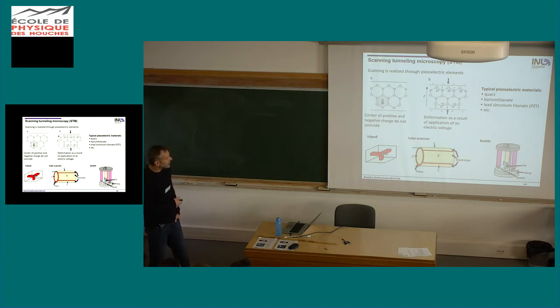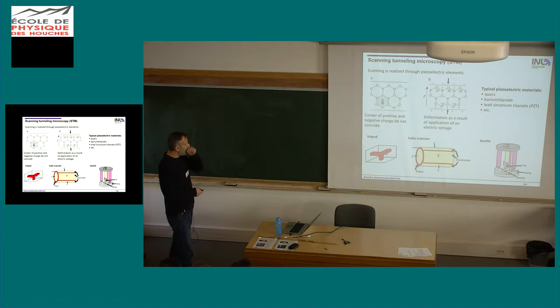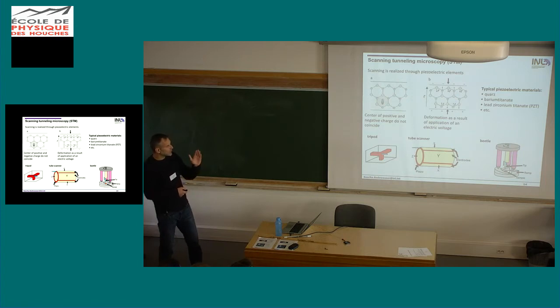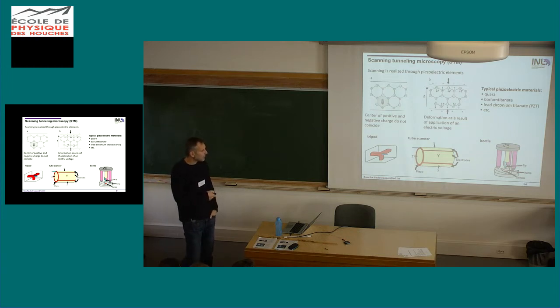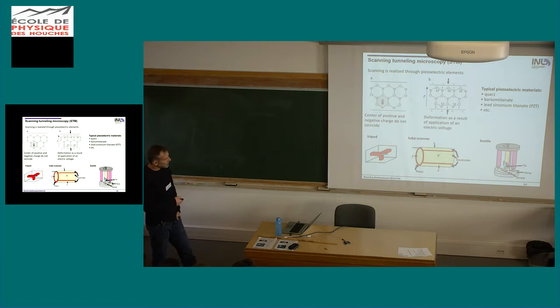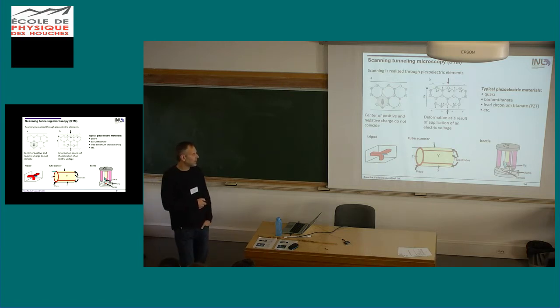And these piezoelectric elements can be designed in different ways. A very simple one is a tripod here. The most commonly used one is the tube scanner. So you have actually a ring, a cylinder of this piezoelectric material, and then you have an electrode on the inside, and you have patterned electrodes on the outside. So depending on how you apply voltage to the Z, the Y, and the X, your tube starts deforming in a specific direction, or if you apply the same voltage to Z and X, then actually you can move the tip forwards and backwards. So with this one you can get all three directions in this design, of course with this one as well. And then another typical form that is used in a lot of homemade systems is a beetle type. So you have the tube here. This is for fine scanning the tip.